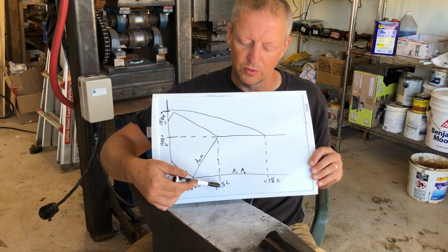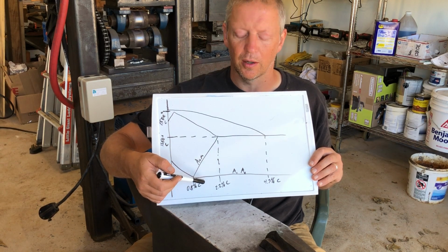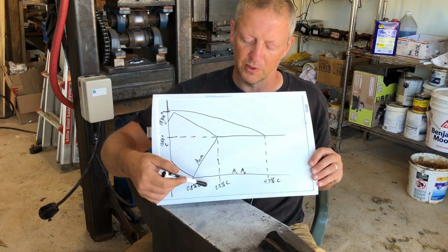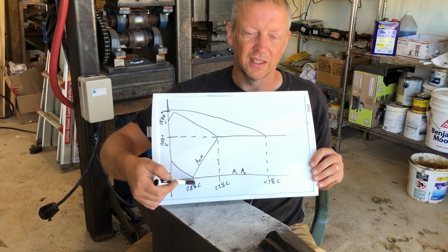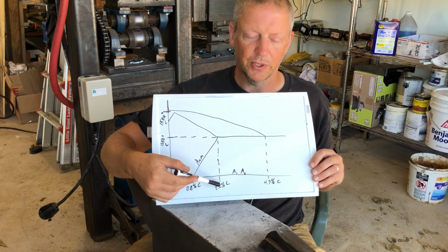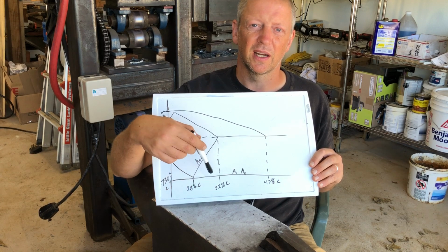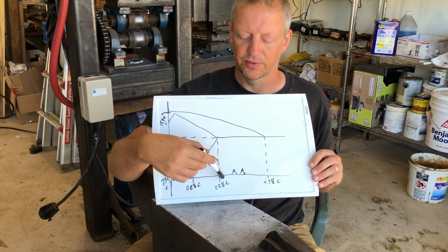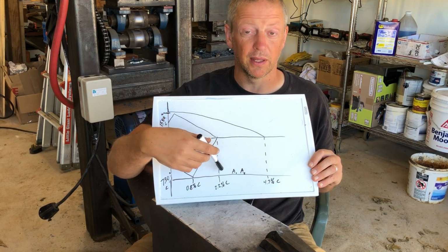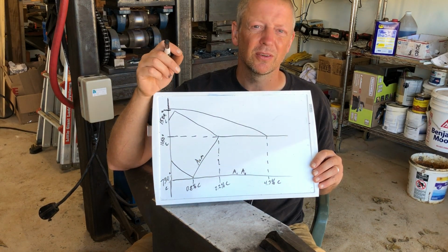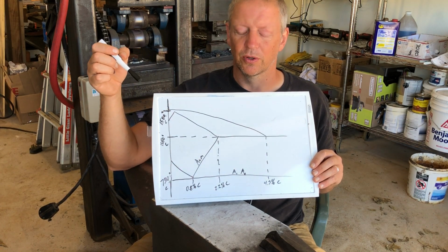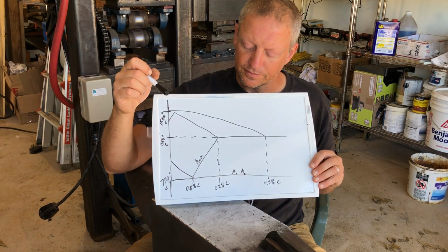And to this side, between about 0.8% carbon and 2.2% carbon, we have the hypereutectoid steels. 2.2% carbon, theoretically, is the beginning of cast iron. Now, there are steels that really play with that line some, but you don't really see them much because you get into very frisky territory there.